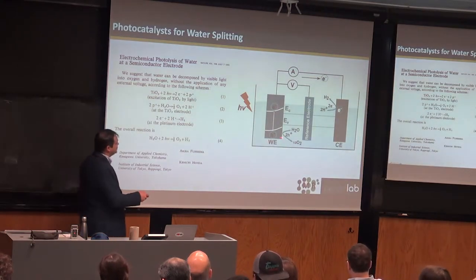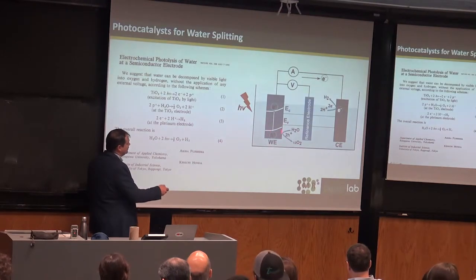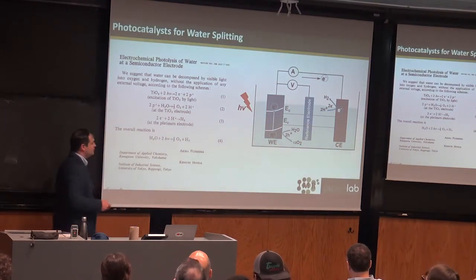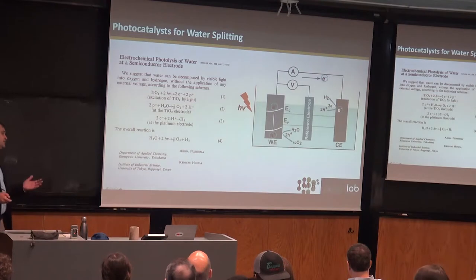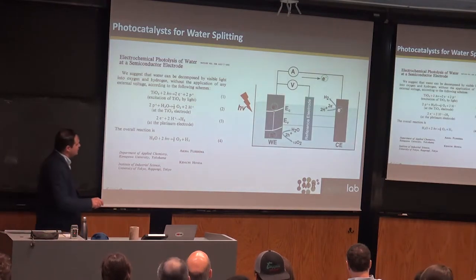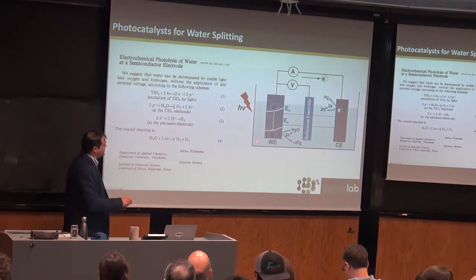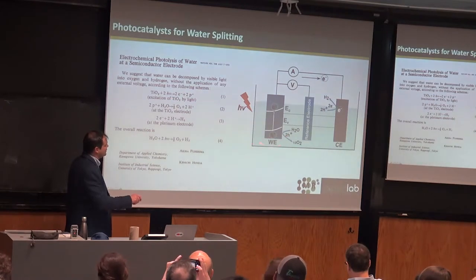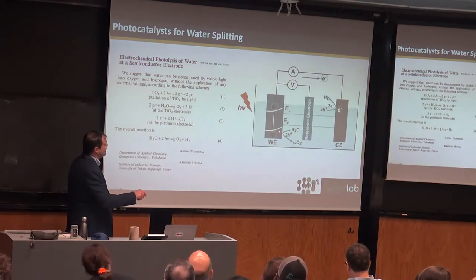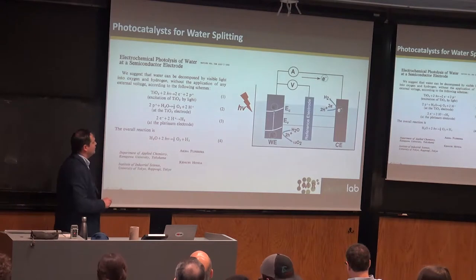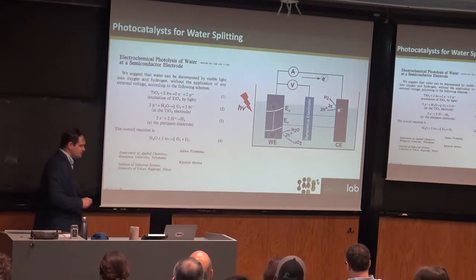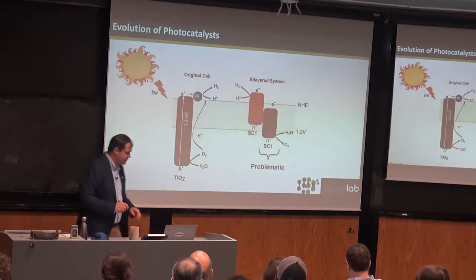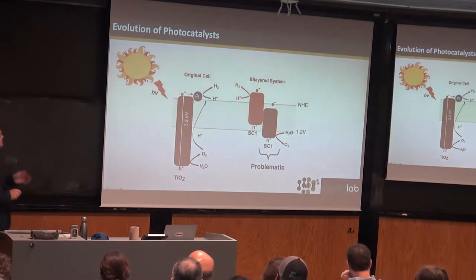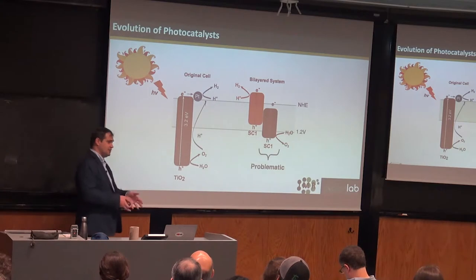And the reason for the overpotential is because of this poor alignment here. So you wanted a stable metal oxide in your aqueous solution. At the same time, the use of a stable metal oxide meant your valence band edge, where your holes are generated, is poorly offset with those redox potentials. So this has prompted a lot of people to view it as, since then, the main focus is: can we shift it to the visible light regime?